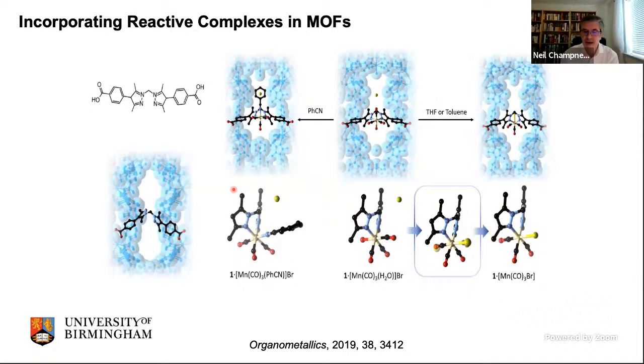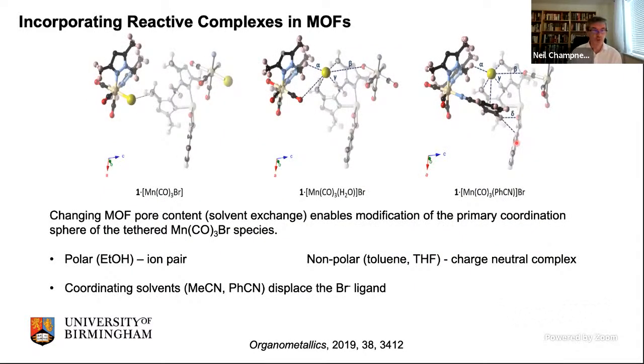So here you can see the compound I just described. We have a bound water and a bromide counterion within the framework. If we use a coordinating solvent such as benzonitrile or indeed acetonitrile, then that nitrile group binds to the manganese. We still have a bromide counterion. If you use a relatively non-coordinating solvent, so THF or probably toluene, you end up with a bromide coordinated to the manganese center. And in fact, you can interconvert between these different states by soaking your MOF crystal in different solvents.